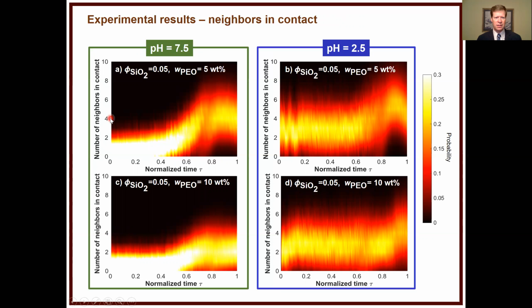And you can see at the end, your neighbors in contact, and this is in 3D, are probably somewhere between 3 and 6, or maybe even 7. And you can see that's lower, in fact, for higher concentrations of polymer because the particles just can't approach each other as well, since there's some polymer left in the interstices between those particles. In contrast, when you have particles that are attractive at the onset, we're going to see wild fluctuations, but you can see the average still, like it's a strong gel, which has on average 3 nearest neighbors and forms a fully connected network.